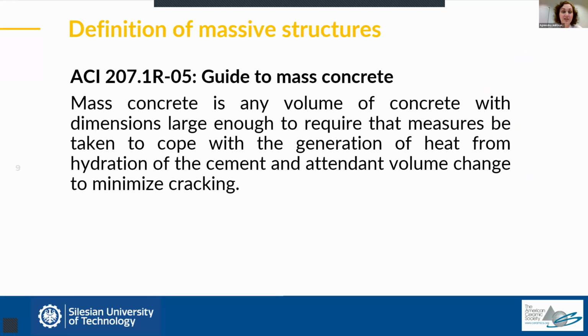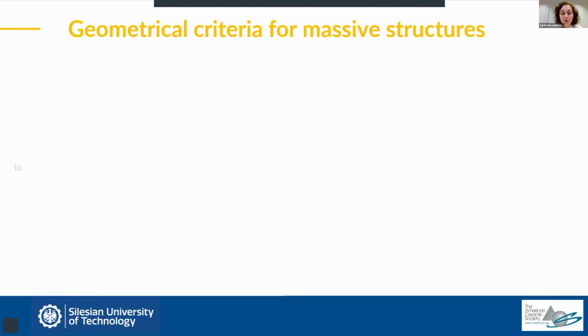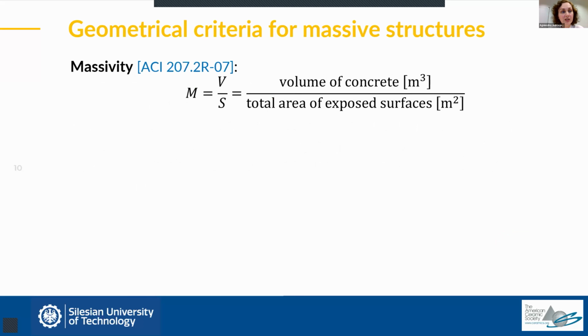So on one hand, we may say that this definition is very understandable because, as I said, we usually connect massivity with volume. But on the other hand, still, I believe, and a lot of people believe, that this measure is not very quantifiable. That's why we relate to other measures, and what comes to hand are geometrical criteria for massive structures. So again, this same guideline provides some measures for massivity, which relate the volume of concrete to the total area of exposed surfaces, which means that one component, the volume, will tell us how much heat will be produced, and the other component, the area of exposed surfaces, will tell us how quickly this heat can dissipate from the element, which will directly affect the internal temperature.